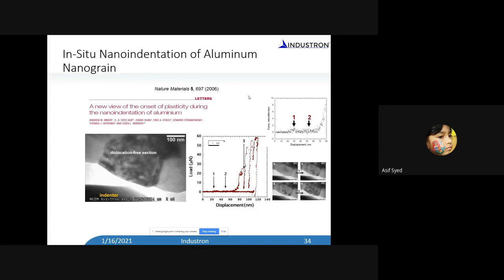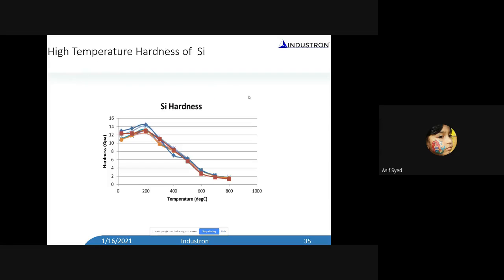This was done in 2006, many years ago. Now we can use these tools inside the SEM or a TEM, apply the load and measure the displacement, calculate the stresses that you are applying, and see directly what is going on within the specimen, so you can have a direct correlation. You don't need to make any assumption. You can see, and then you can believe what's going on. So that is the power of this kind of technique.